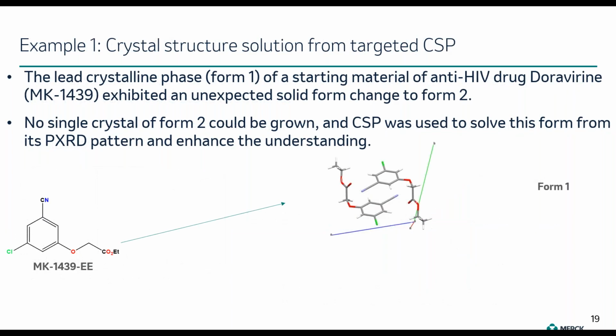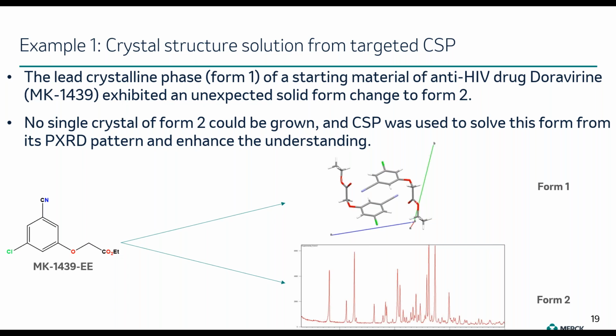I'm going to show you two examples. The first one, we did a crystal structure solution from a very targeted CSP. In this case, the compound for which we were trying to solve the crystal structure was the starting material of the anti-HIV drug doravirine, or MK-1439. The lead crystalline form 1, for which we had a full single crystal X-ray diffraction solution, underwent an unexpected solid form change to form 2. However, we could not grow any single crystal for form 2, but we could only gather powder X-ray diffraction data, and we chose to use CSP just to solve the crystal structure of form 2 of this compound.